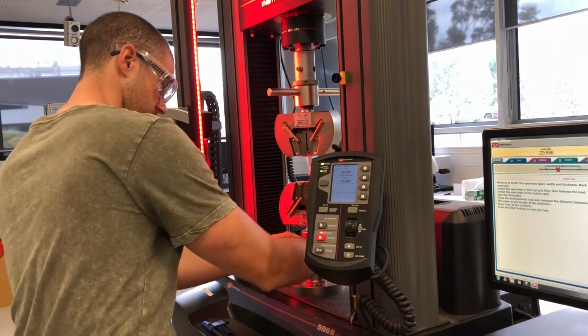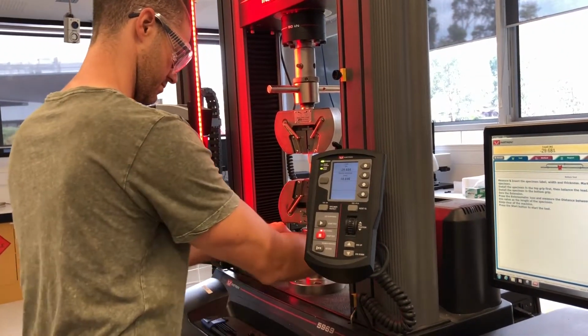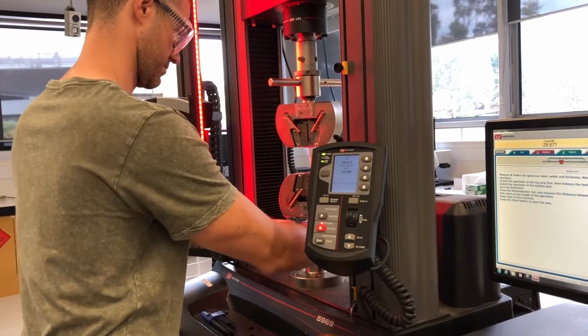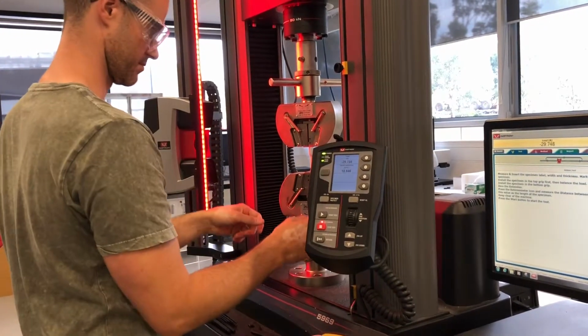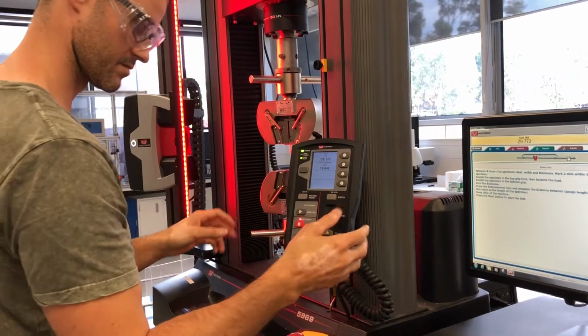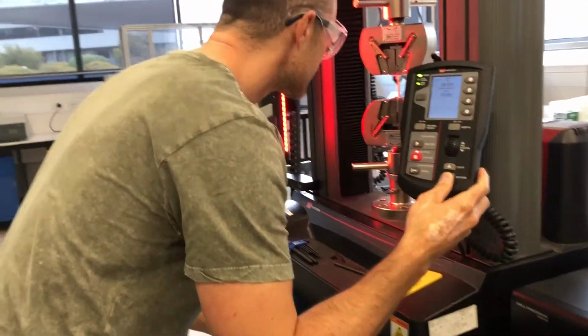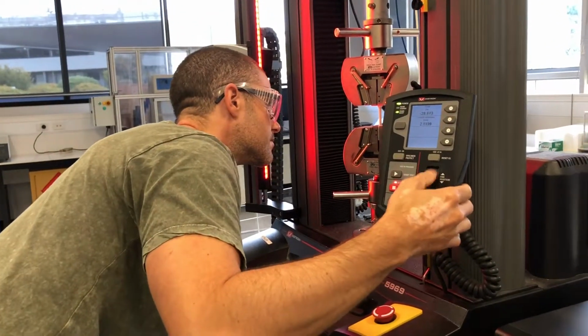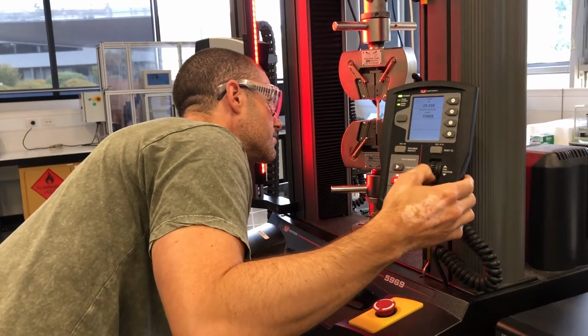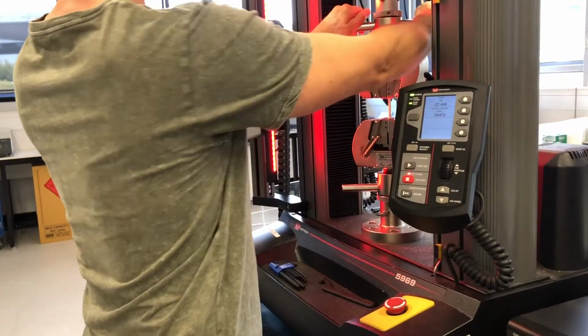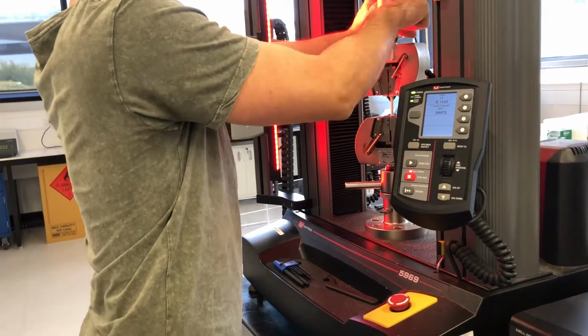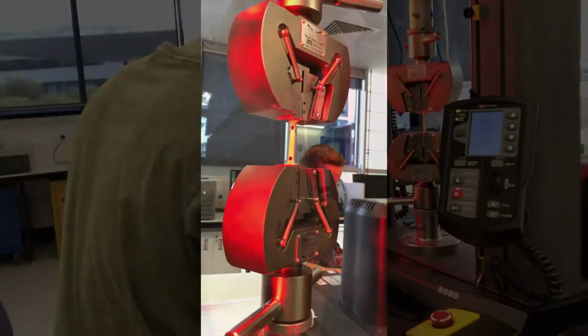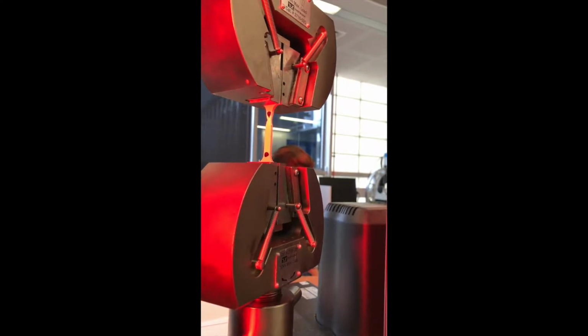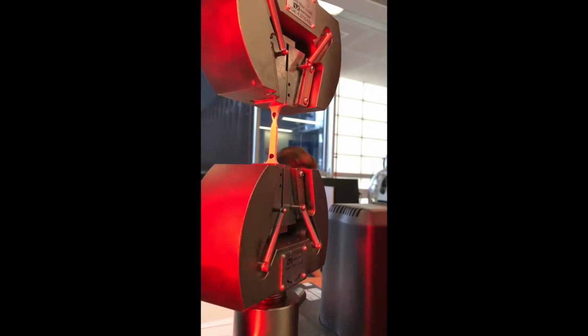The tensile test machine then slowly stretches the material until breaking point. Our 3 samples had an average offset yield strength of 33.75 MPa and a standard deviation of 0.3, an average ultimate tensile strength of 35.04 MPa with a standard deviation of 0.1, an average Young's modulus of 1.1 GPa with a standard deviation of 0.1, and an average maximum elongation of 61% strain with a standard deviation of 13.